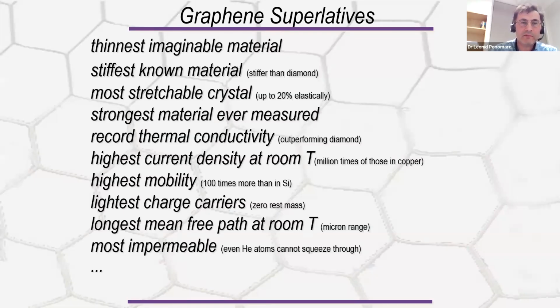But it has many other interesting properties. First of all, mechanical properties. If we calculate the stiffness of this material, of course per unit of thickness, not absolute stiffness, this would be the stiffest material known. It's stiffer than diamond. At the same time, this material can be stretched quite a bit before it breaks. So this is the most stretchable crystal. We can stretch it up to 20% and it still doesn't break. These two properties together, stiffness and the fact that we can stretch it quite a bit, make graphene the strongest material ever measured.